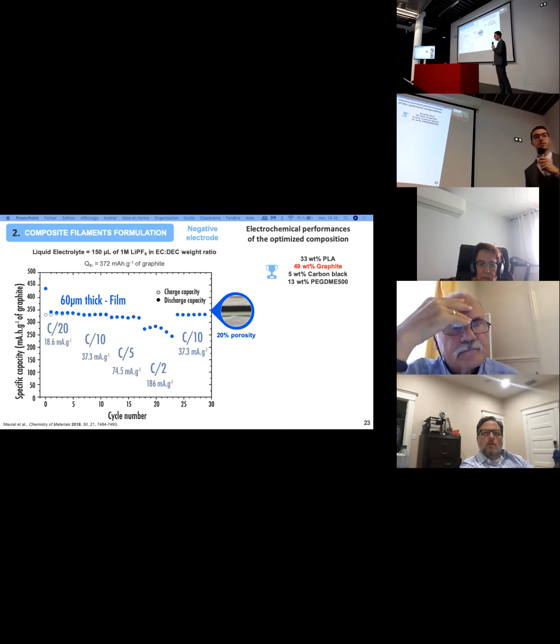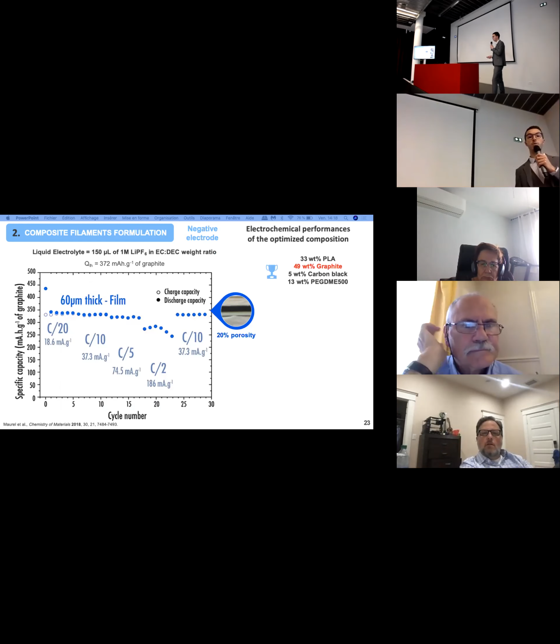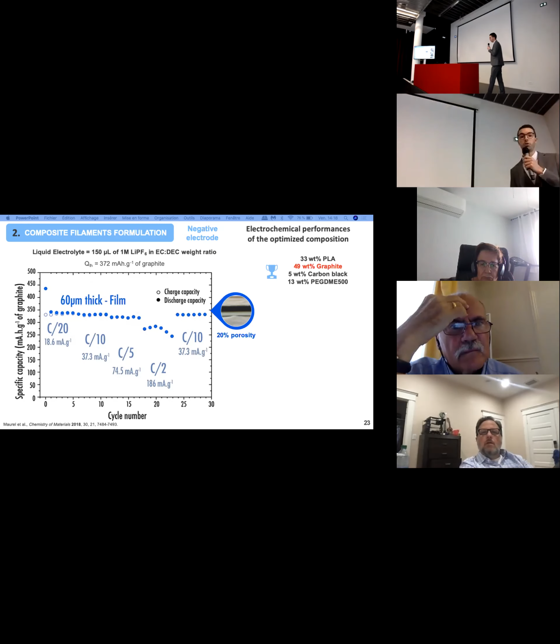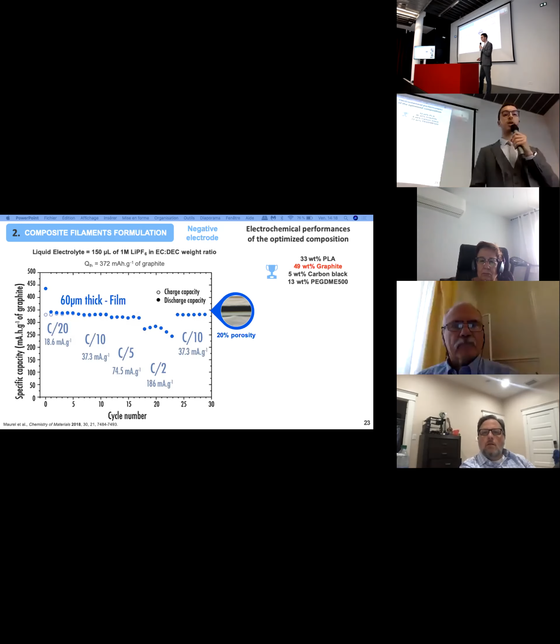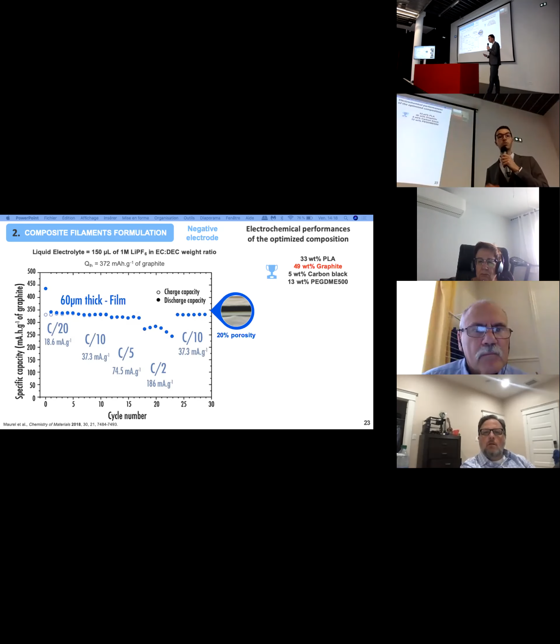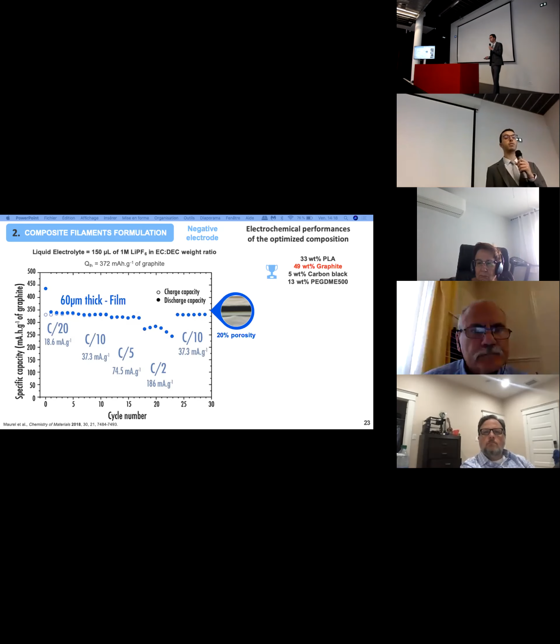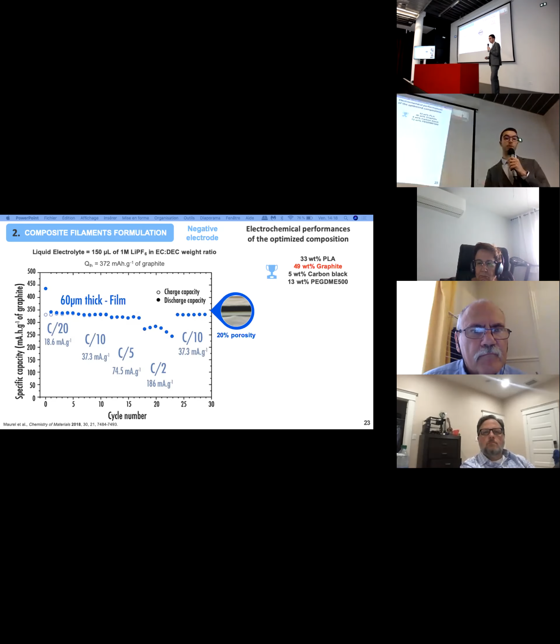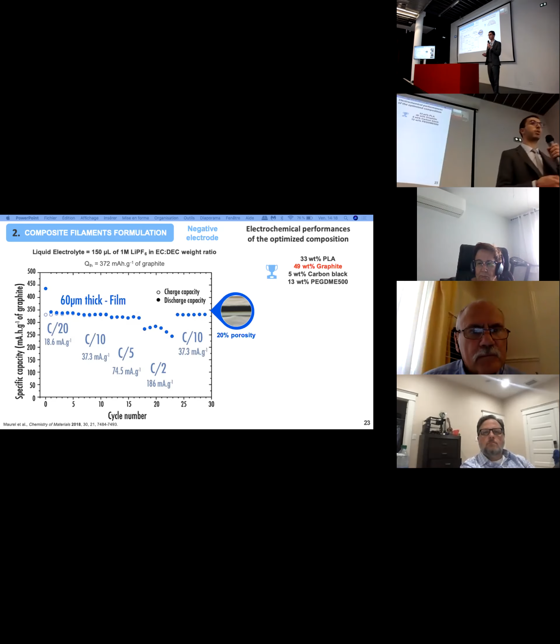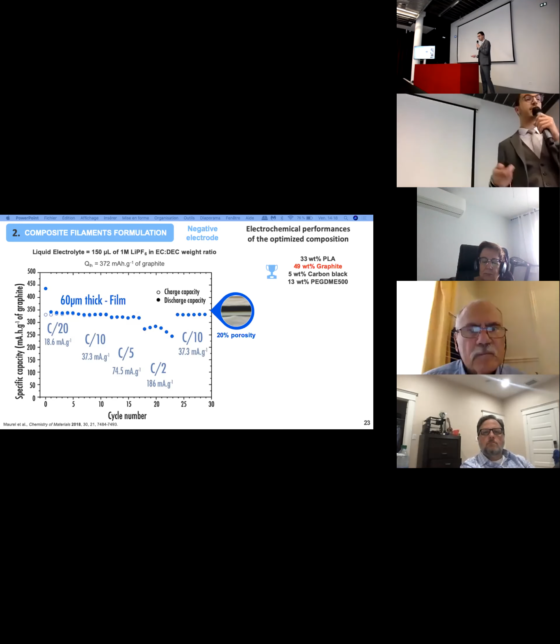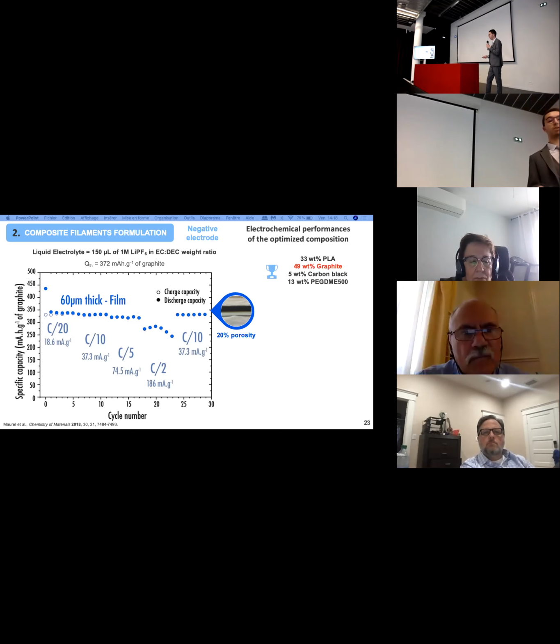So for the films, as you can see, with the optimized value, we were almost reaching the theoretical capacity of graphite, the active material, which is about 372 milliampere hours per gram. And as we were reaching almost this theoretical value, we then tried to produce a filament, and we printed some discs. These discs, again, were tested electrochemically.